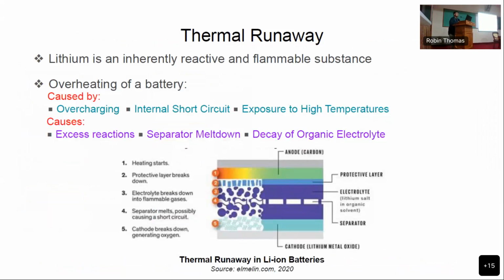And thermal runaway. Thermal runaway refers to temperature-related causes, and overheating of a battery can happen internally or externally. Externally, when we are overcharging the battery or exposing it to high temperatures, and internally when there are short circuits due to maybe dendrite formation or anything. So this causes excess reactions and separator meltdown. The separator is essentially what is keeping the electrodes apart. So if the separator melts down, there is every chance on the planet for the electrodes to touch each other and cause a short circuit.